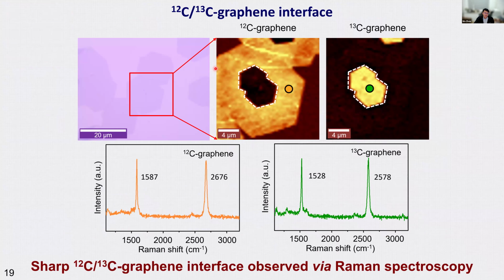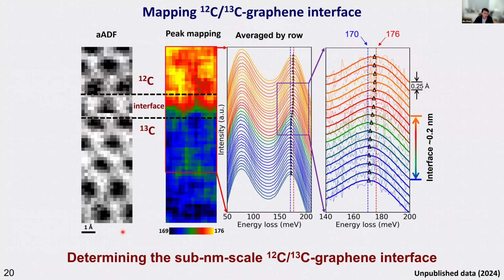The first one we look at is a carbon-12 and carbon-13 interface, made just by switching the methane source precursor during the growth. You can first identify the macroscopic interface using Raman mapping and then put it into the electron microscope. From the ADF image, we would not expect that we can tell the difference between carbon-12 and carbon-13, because this image mode is only sensitive to atomic number. But if we map out the optical phonon peak position in this area, we can actually see that the top part has a higher frequency, corresponding to carbon-12, and the bottom part corresponds to the heavier atom, carbon-13.